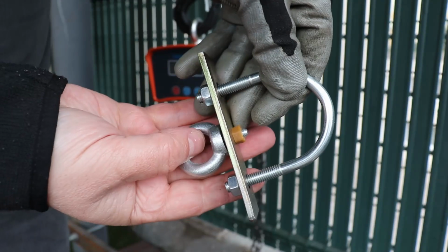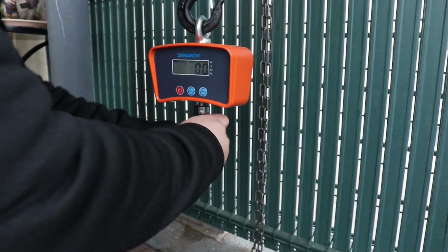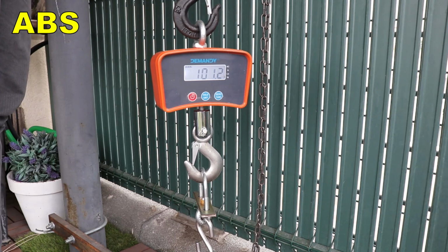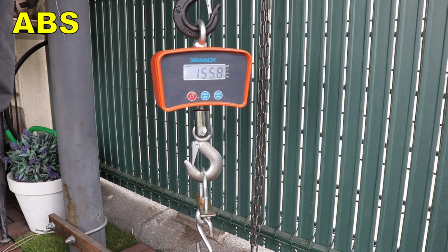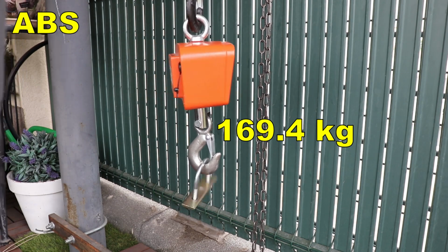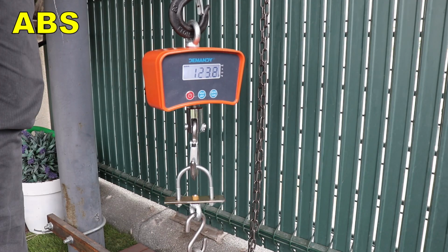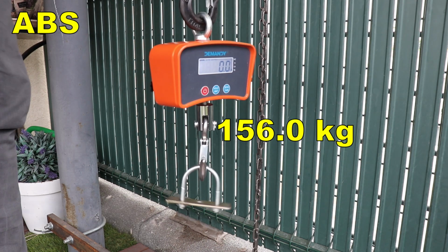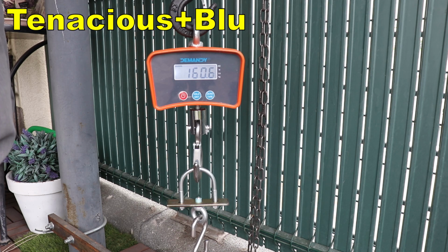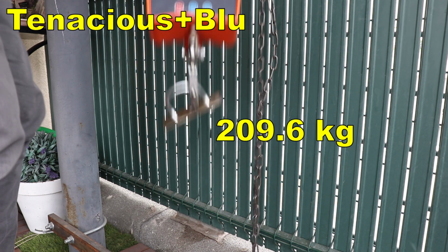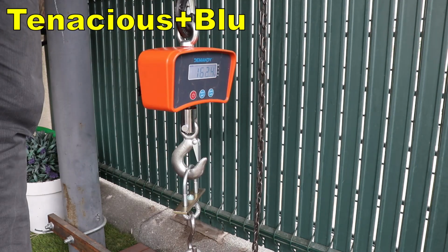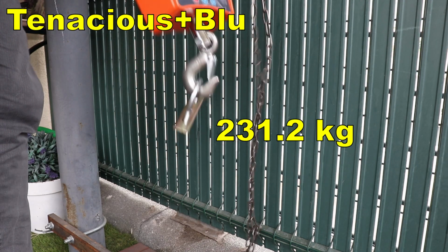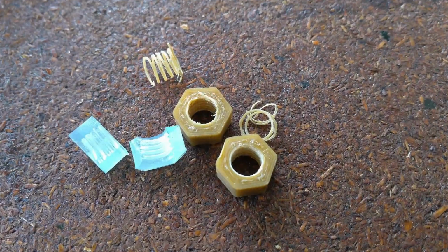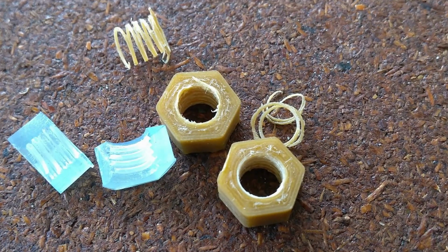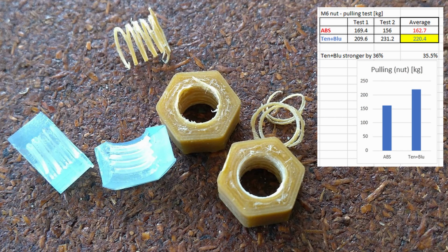And this is the pulling test for the screw nuts. Actually, it will be a shear stress for the threads, at least in the case of the filament ABS, because you will see here in the case of the ABS, the thread was pulled out from the nut in both cases, but the resin ones just exploded, at a much higher load. And same with both test specimens. And here you can see I couldn't find all the pieces. And here the resin was stronger by approximately 36%.